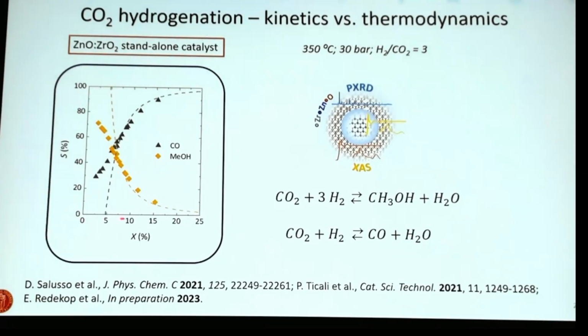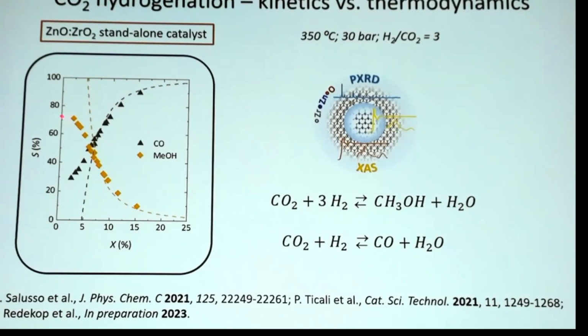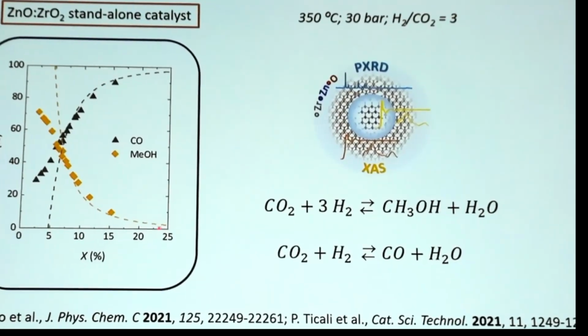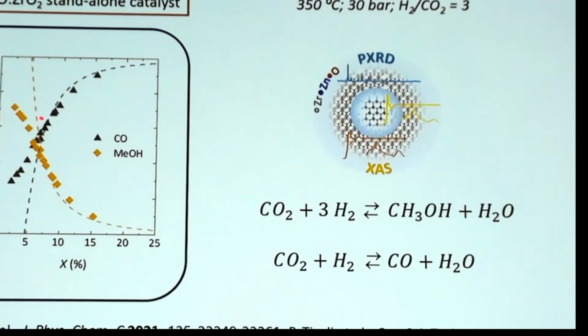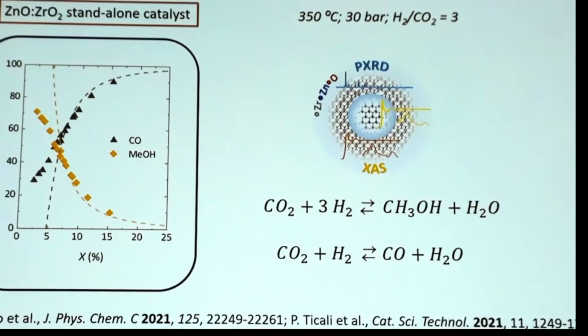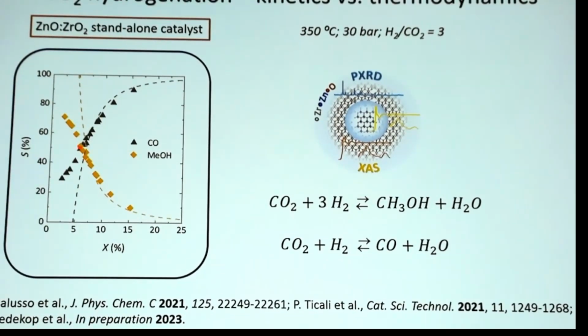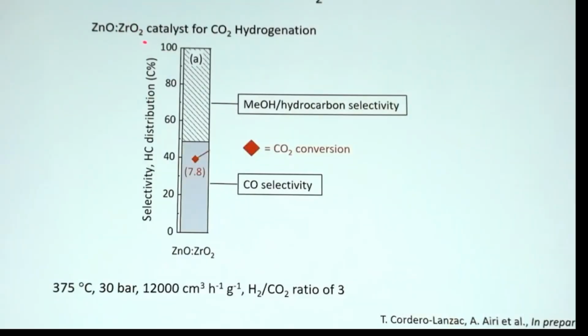So this is the increasing conversion of CO2, and we see here the selectivity to methanol, which is decreasing with increasing conversion of CO2, and then we see the CO selectivity coming up. And you see already at about 5% conversion, these products are at equilibrium. They are following the dotted line, which is the equilibrium here. So methanol is the first product, but it's limited by equilibrium.